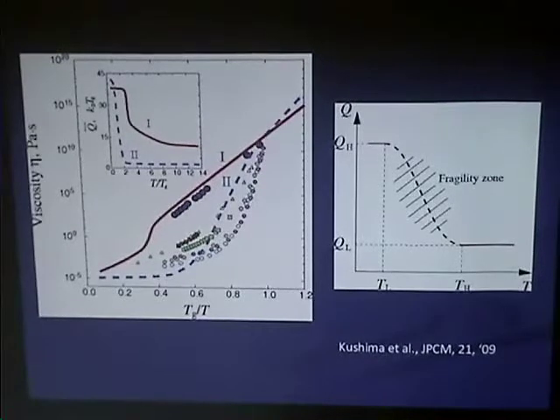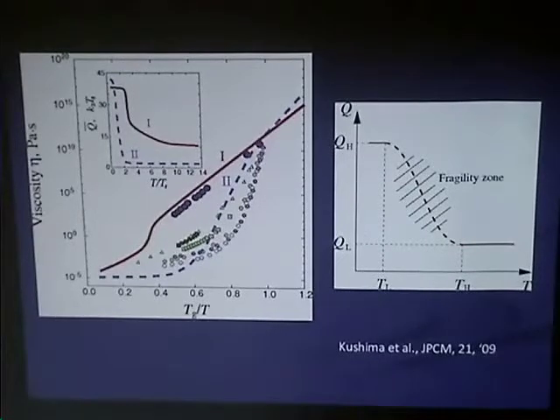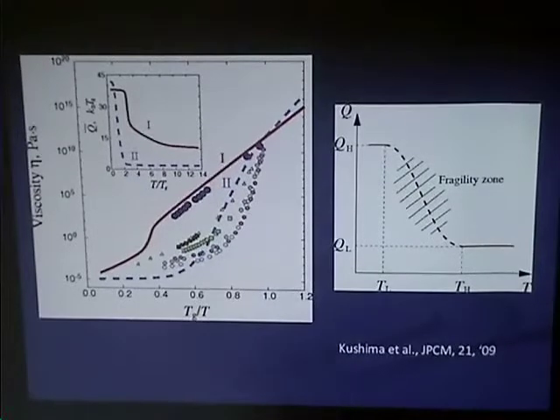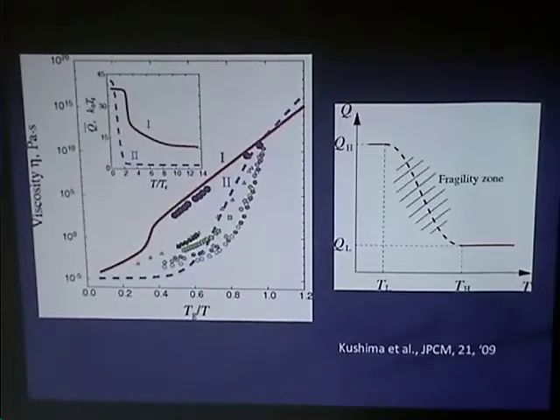That is true, but if TG is just a translation parameter, so why doesn't that translate from this thing here? The log viscosity, A to T - if I take the log, I get Q over T. So the slope of a plot of log viscosity against 1 over T is Q.